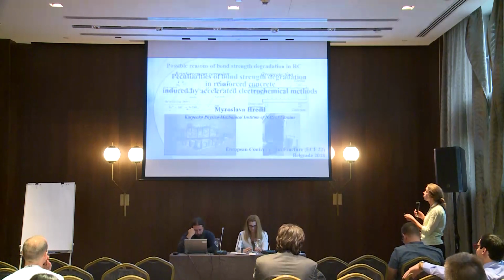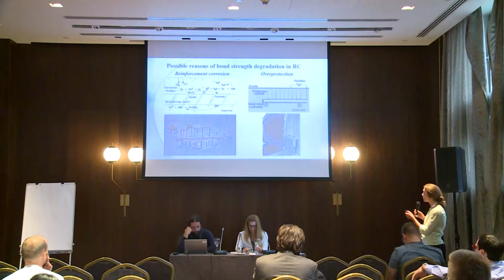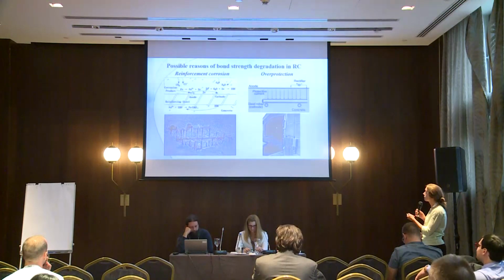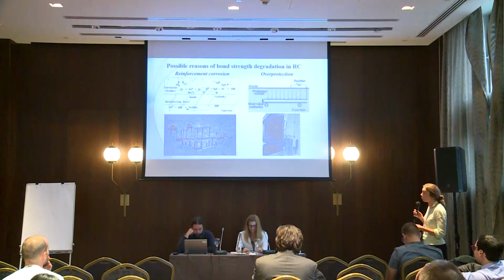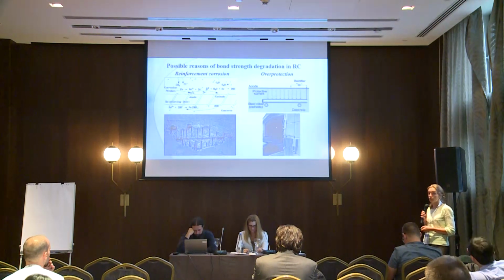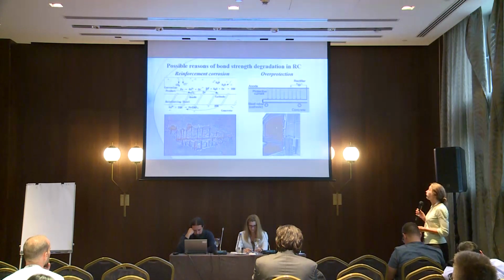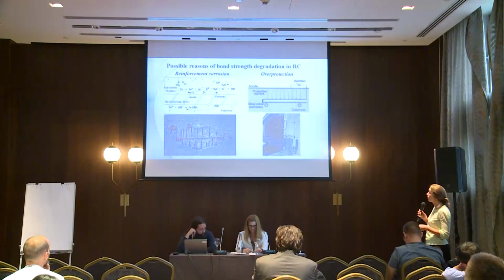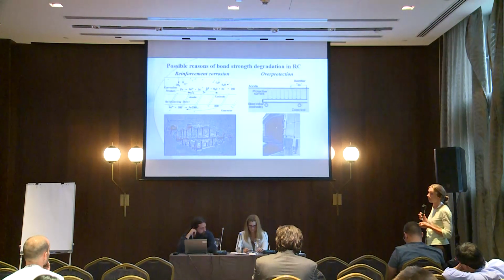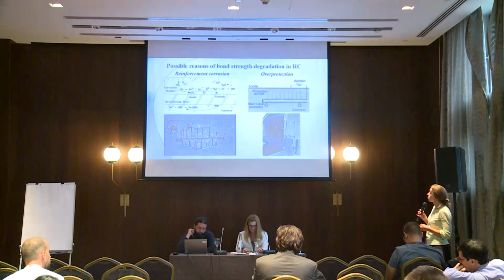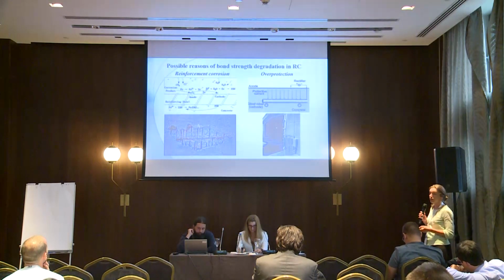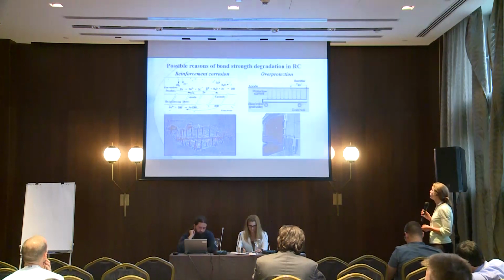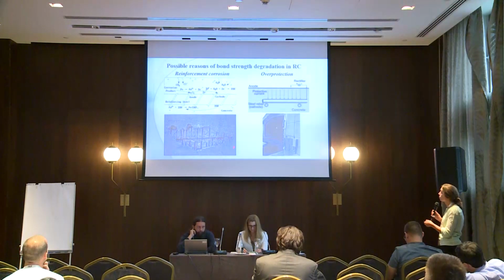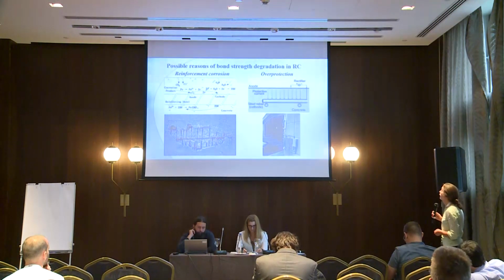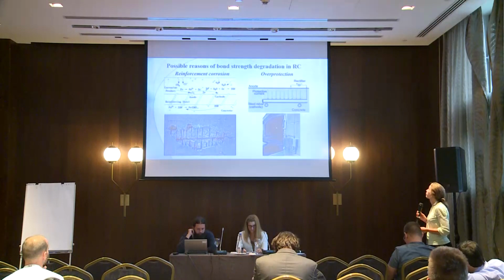Accumulation of corrosion products at the steel concrete interface, whose volume is larger than the original iron volume, leads to creation of internal stresses at the interface, and this promotes cracking and spalling of concrete cover. An example of this effect you can see on this slide.